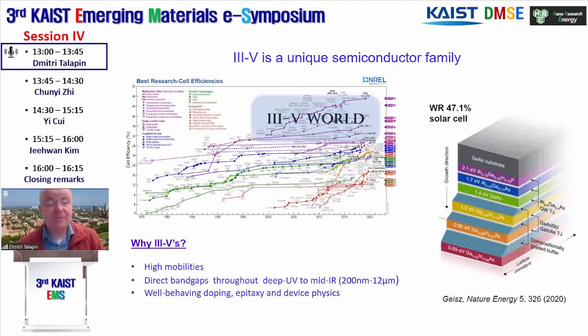And as a starting point for this exploration, we decided to focus on a very important challenge in the field of colloidal quantum dots, which is the synthesis of III-V quantum dots beyond indium phosphide, indium arsenide, and indium antimonide.